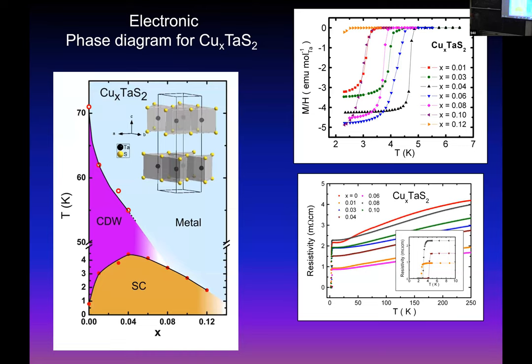Amongst the ways to get superconductors is to get something that's electronically unstable and get it to do superconductivity instead of what it really wanted to do. There are some states that are believed to give rise to superconductivity when they're destabilized. The copper oxide superconductors, like you just saw, are one example, because they're magnets under ordinary conditions. They're antiferromagnets, the spins are aligned opposite. When you kill the antiferromagnetism, superconductivity evolves.